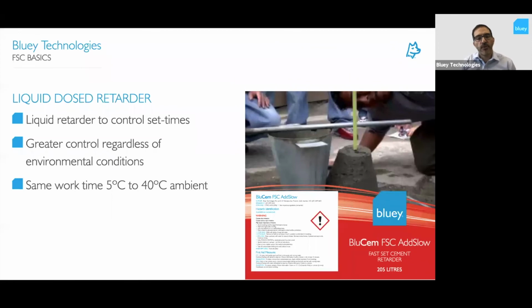By adding a liquid retarder with controlled dosage through the truck, we can actually set the amount of retarder that we're adding to the powder so that we can set the work time to suit the ambient conditions. So whether we now have a 5-degree day or even closer to a 0-degree day, or a 40 or even 45-degree day, which we've worked in before, we can actually have a set time of 30 minutes or 40 minutes as per the contractor's instructions.